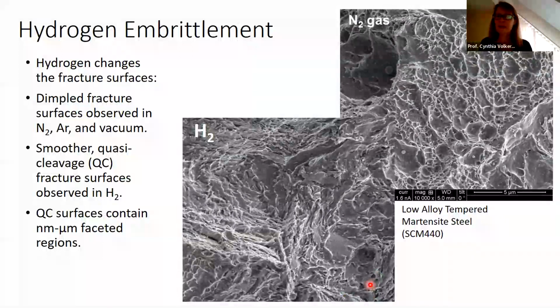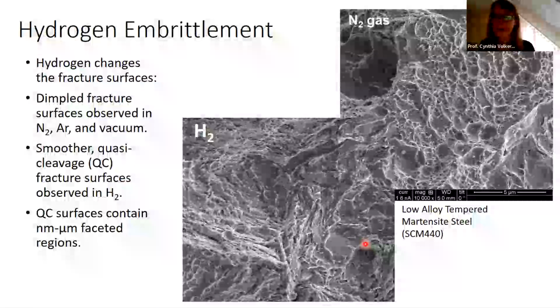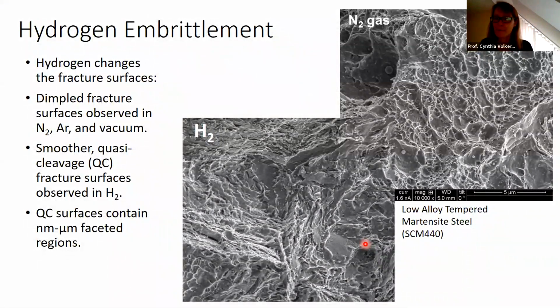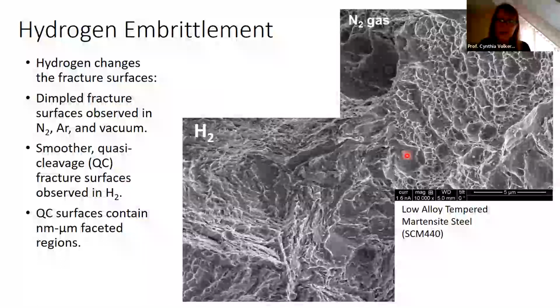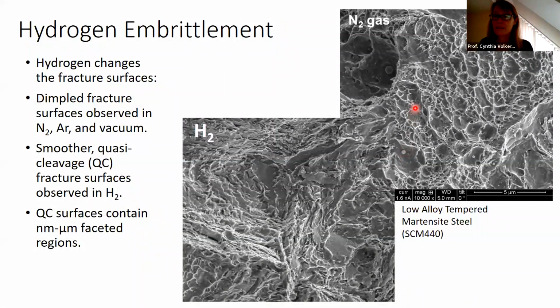And if we go in and look more carefully, one finds really very distinct features on the surfaces. At first glance, maybe if you're not used to looking at these, you think, well, I don't see big differences, but in fact, there really are important differences. If you take a look here at the case that's fractured in nitrogen gas, and if it were fractured also in argon or vacuum, it would look similar, we have features that we call dimples. There are small openings, and as has been concluded throughout the literature, these kinds of dimpled surfaces result from voids forming and coalescing at the crack front, and what you see here is basically half of the side of a void, the surface of a void that has coalesced to form this fracture surface. So that's what we see here. You will also see these occasional features like this one I'm pointing at right here. That is a carbide precipitate, and those are found on the surface of these fracture surfaces.